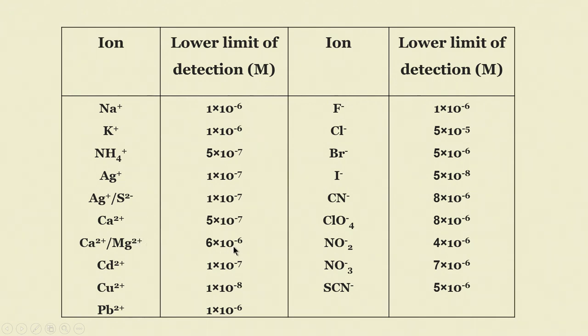Then calcium, magnesium, almost all of them, cadmium, copper, and these two are 10 raised to minus 7 and 10 raised to minus 8 molar concentrations. That is fantastic actually. And that is why we always say ion selective electrodes are very important if you want to determine very low concentrations of the solution in molar quantities, and the response would be linear over several orders of magnitude.